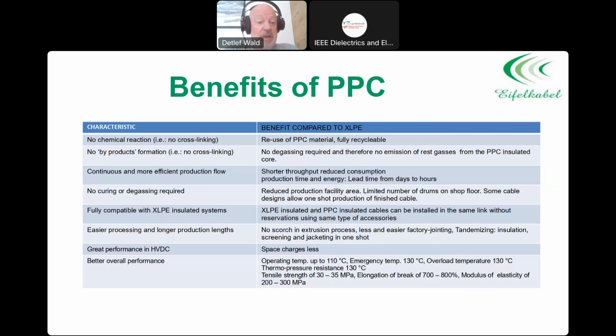Also, since you don't have any curing, your production lengths can be longer because you don't have any scorch. That means no pre-cross-linking of the material. On the other hand, making a factory joint is easier because the factory joint doesn't have to be cross-linked. You just make it thermoplastic.